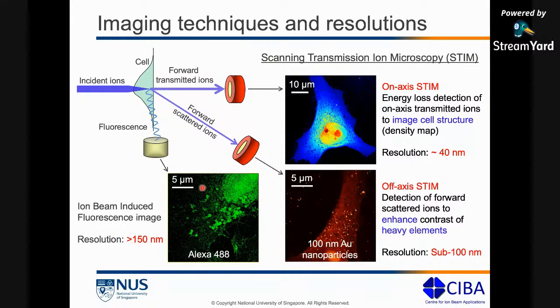And here, this is just a fluorescence detector that we sometimes place in there in case you have fluorescent particles in your cell. We can detect these fluorescent particles using this fluorescence detector. But the idea being that the fluorescence, compared to the on-axis and off-axis STIM, gives a very poor resolution. So we typically don't do this unless it's absolutely necessary. We stick with on-axis and off-axis STIM imaging, and within this we will mostly stick to off-axis STIM imaging because we have this additional advantage of elemental contrast.